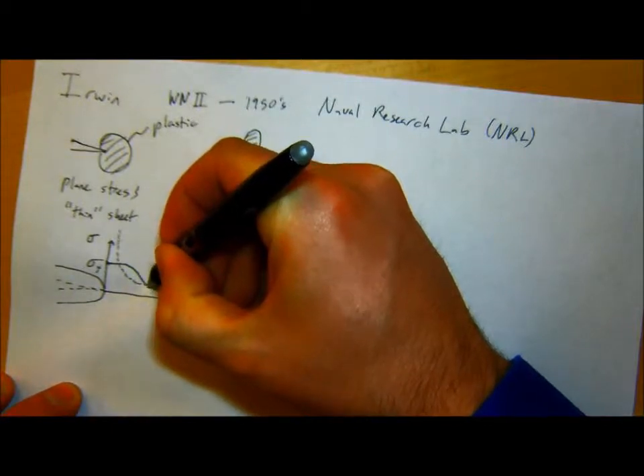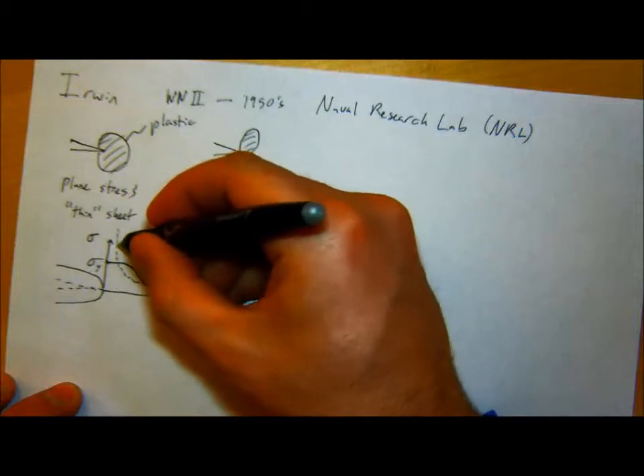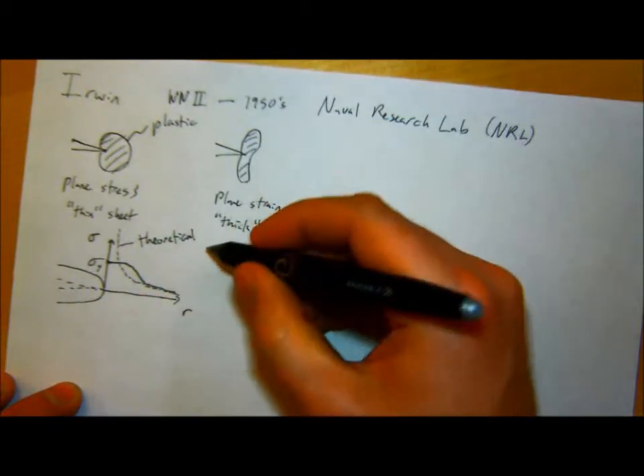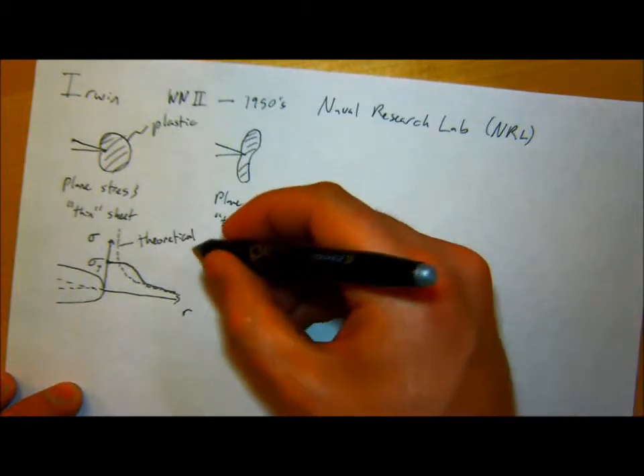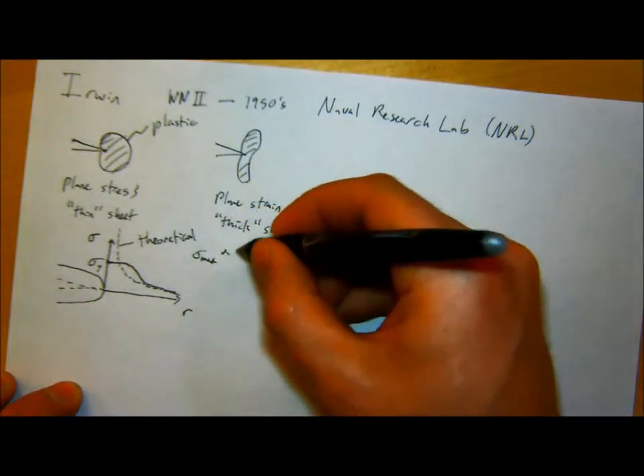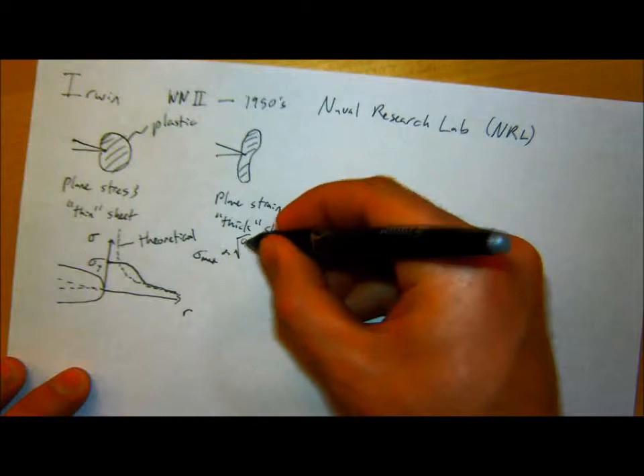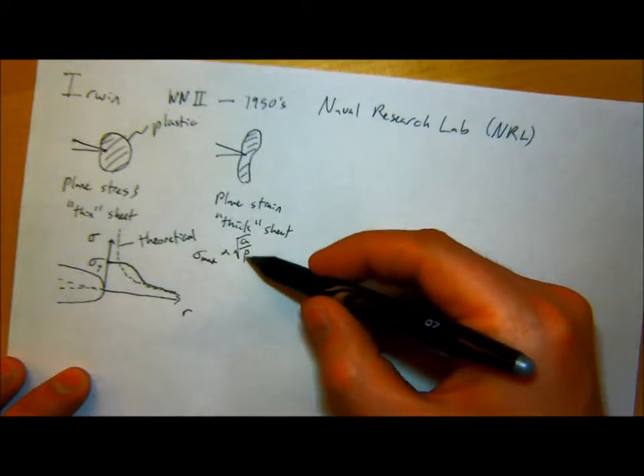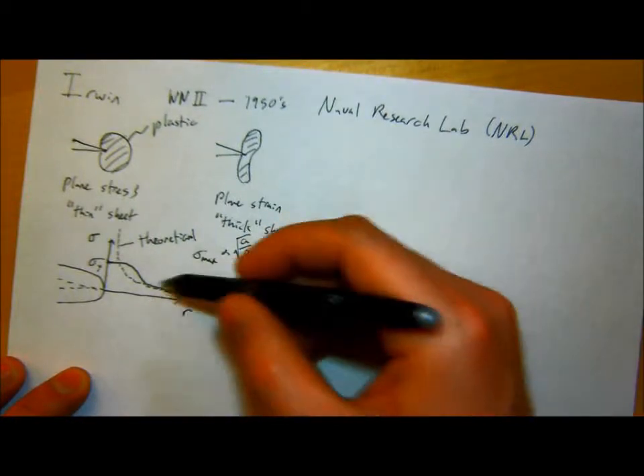So this is the theoretical, that sigma max is proportional to the square root of a over rho, where rho now is the radius of our tip. So if I make that crack infinitely sharp, it goes up to infinity. This is now the realistic one, where you have plasticity.